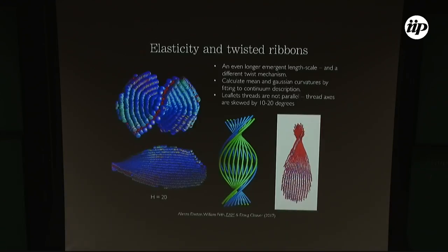And it turns out if you look at those, they form stripes. And those stripes are going to be the little indents where each of the layers of disks sit. So what you're going to see is that if you fit each of these threads to a helix, you get this sort of bilayer structure of helices. And if you look closely just at this point, you'll find that each of the helices on the front layer is offset by a constant angle from the back layer.